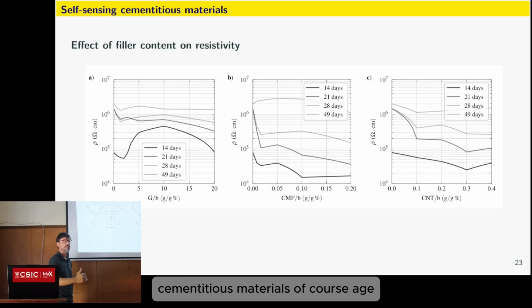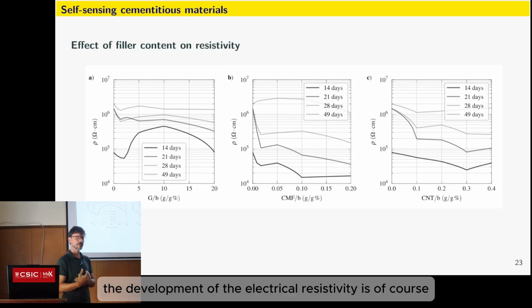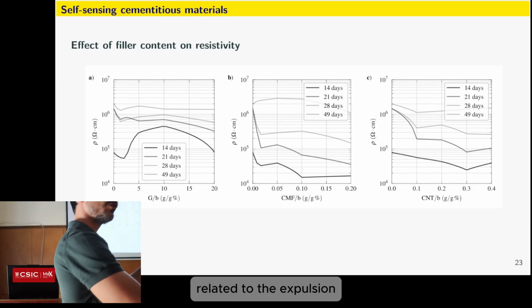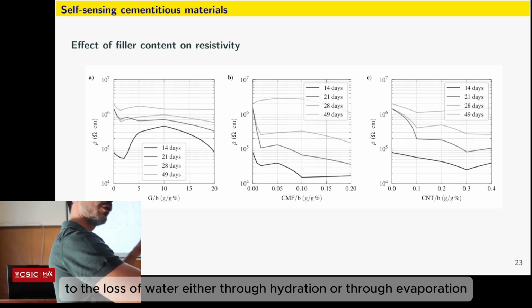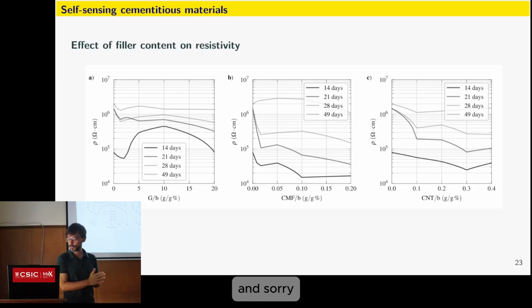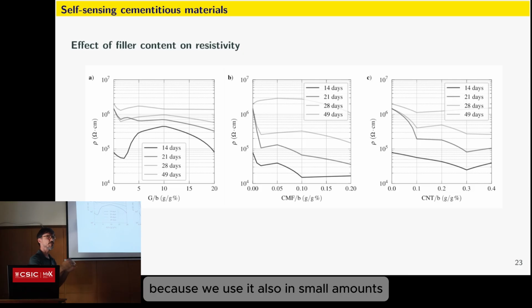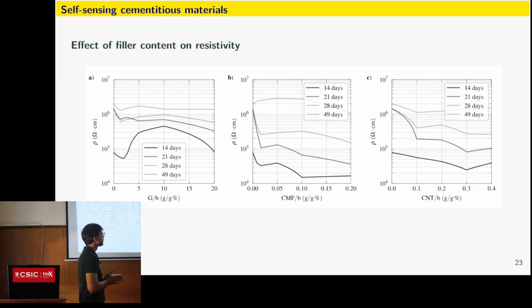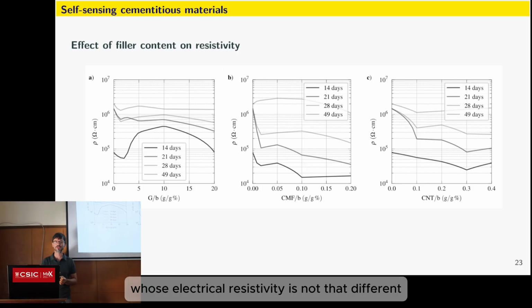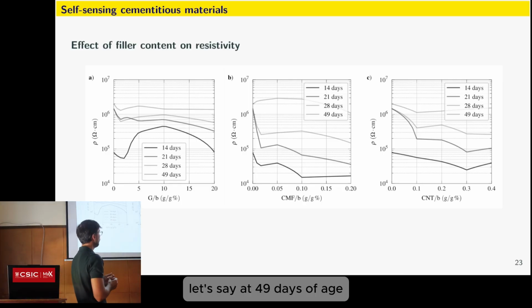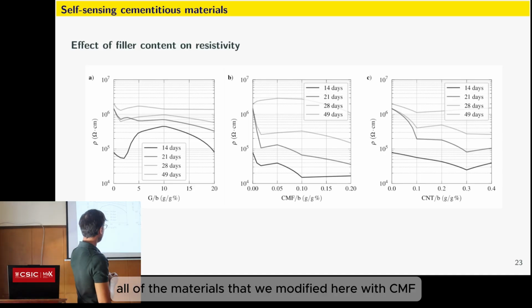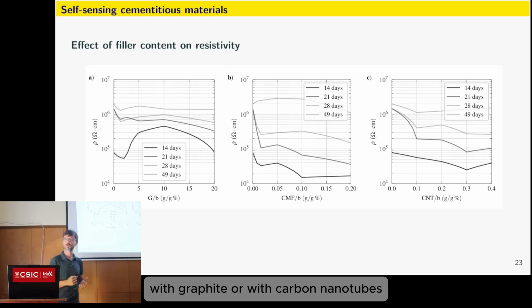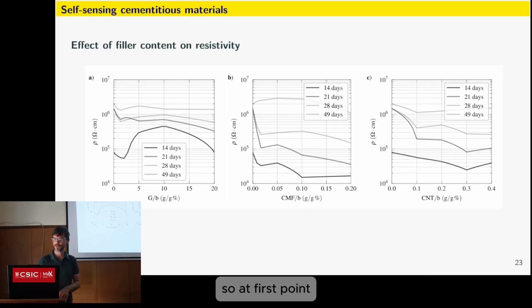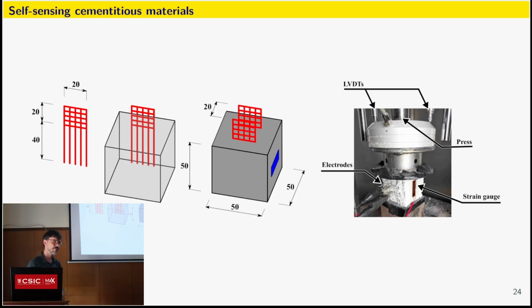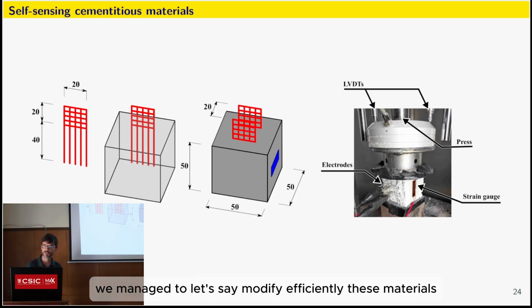So we create these cementitious materials, of course, and they age quite differently depending on the type of filler that we use. The development of the electrical resistivity is related to the loss of water, either through hydration or through evaporation. And independently of the type of filler that we use, because we use it in small amounts, we obtain a material at the end whose electrical resistivity is not that different. Let's say at 49 days of age, all of the materials that we modified here, with CMF, with graphite, or with carbon nanotubes, had more or less the same electrical resistivity. So at first glance, maybe we were not really successful. But as you will see later, we managed to modify these materials efficiently.